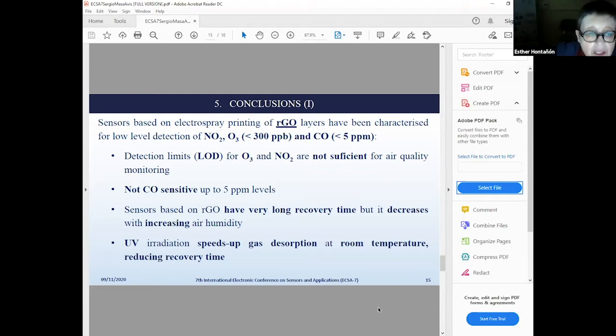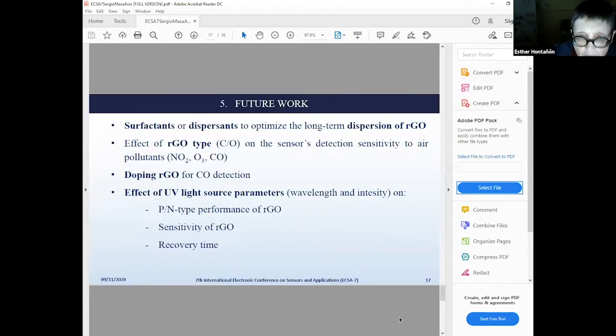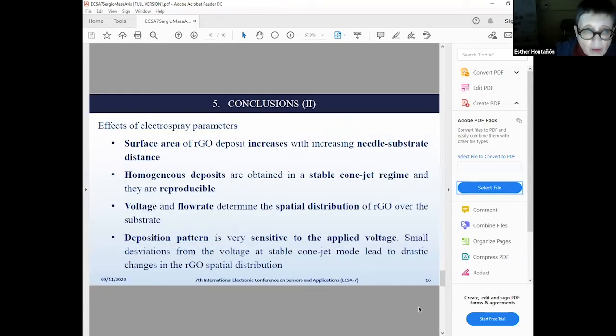But it decreases with increasing air humidity, and can be decreased further by irradiating the sensor with UV light. With regard to the electrospray, we have seen that it is possible to obtain homogeneous and reproducible deposits by operating the electrospray in the most stable cone-jet configuration.